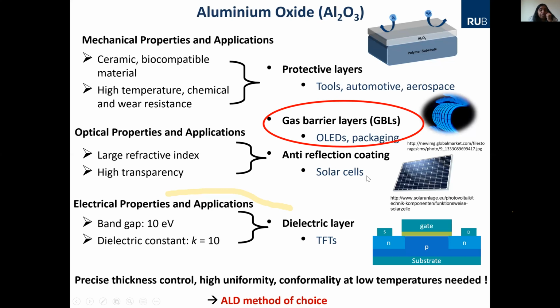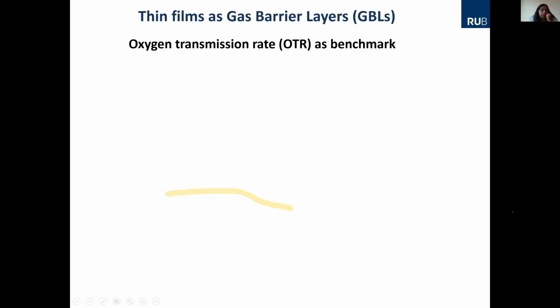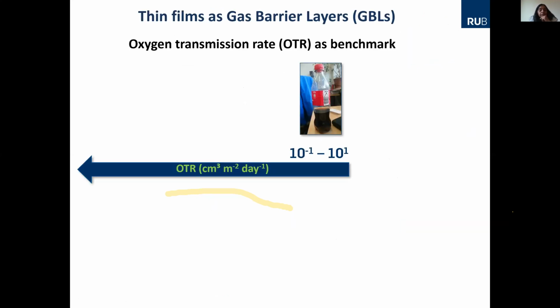So when you want very thin layers, as I said in the earlier slide, you have very good thickness control, good uniformity, and conformality at very low temperatures, and this is where ALD is the method of choice. So we can give an example of why we need this method and why this material is of interest. Imagine you have a Coke bottle. It's basically a PET bottle, right? Polyethylene terephthalate. There's one parameter called the OTR, the oxygen transmission rate. This can be used as a benchmark. The OTR has a unit of cubic centimeters per square meter per day.